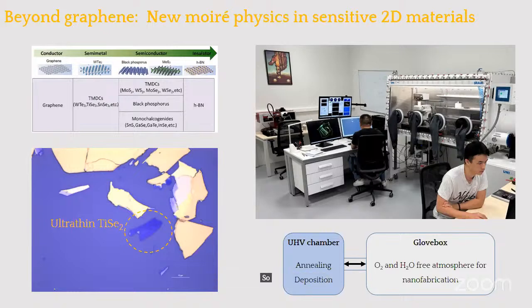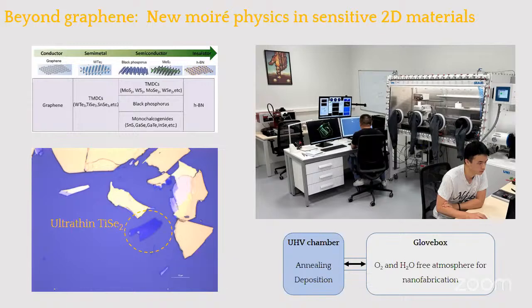So you may have noticed that we have this setup inside of a glove box. In order to do the examples that I showed you with graphene or even MoSe2, it's not necessary to have a glove box because they are inert materials and there are other strategies to clean them up after the fabrication. However, we are keeping this setup inside a glove box because our goal is to extend the moiré exploration beyond graphene.